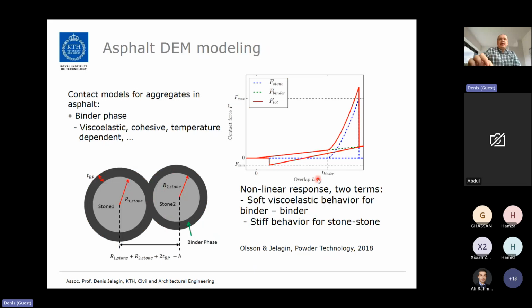And the idea there is that if we look at stones, at some point we have this nearly Hertzian contact shown here with the blue line. But in case we have a certain thickness of the binder film, we have viscoelastic deformation until a certain depth. We have a much softer response, and this part is rate dependent, so it is viscoelastic until we reach the binder film thickness where elastic deformations take hold.